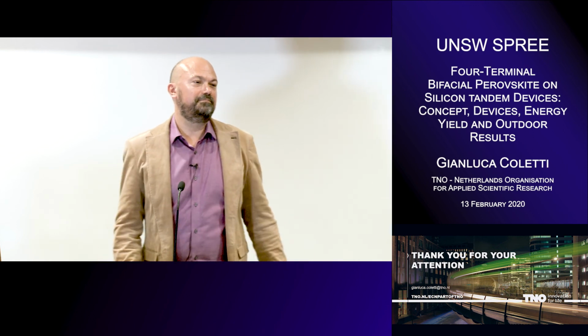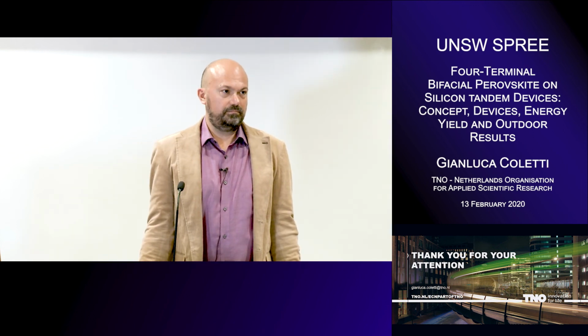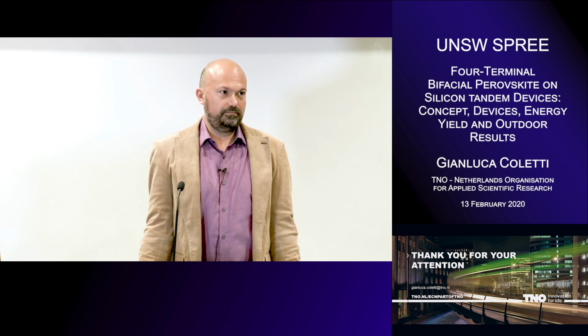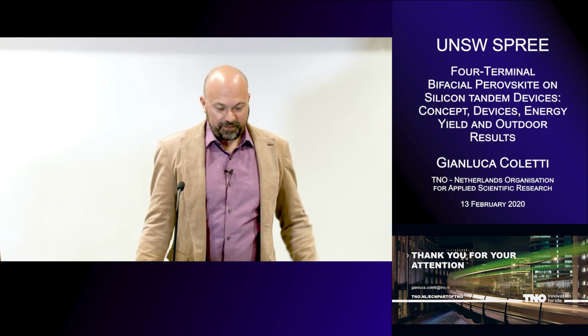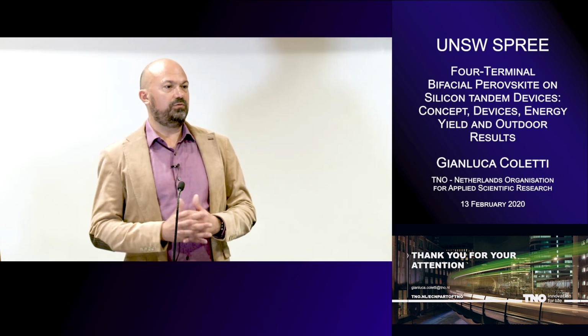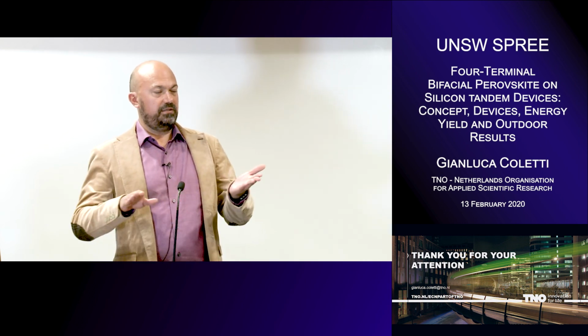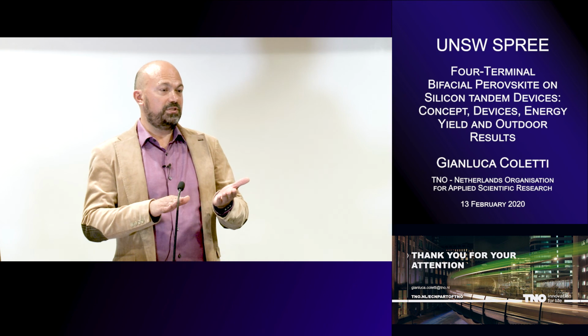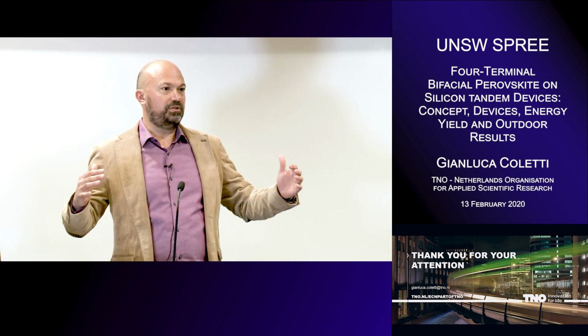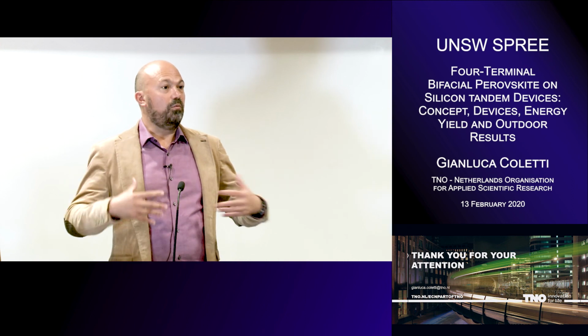Yes. If we can optimize the surrounding condition, would this four-terminal bifacial give the highest power density per area, compared to if we can optimize the albedo? Let's say we have a limited rooftop space and I want to generate the most amount of power. That's what you see when you change the ground coverage ratio, which means the pitch, the distance between modules. So if you want to have the most power, actually you put them the farthest apart, because then you have more of the effect of the albedo.